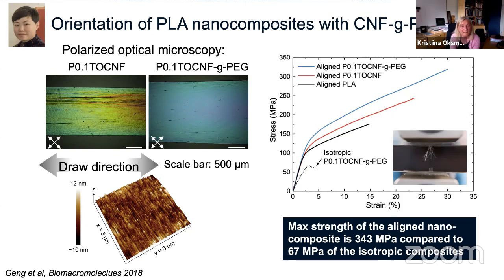And you can also see here, this is the pure PLA, which is oriented. So you can see that this is improving. And then the material where we have just added nanofibers, and then this one where we have this polyethylene glycol, which is improving the dispersion. So the maximum strength is improved from 67 megapascal for the isotropic to 343 for the aligned composites.